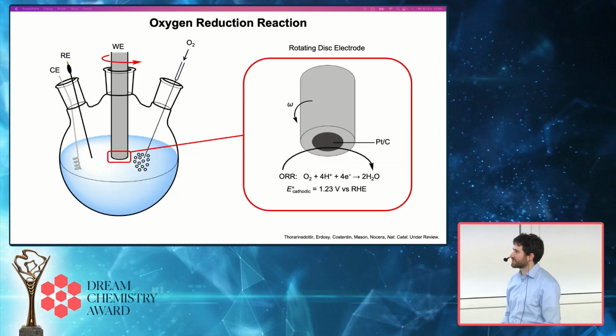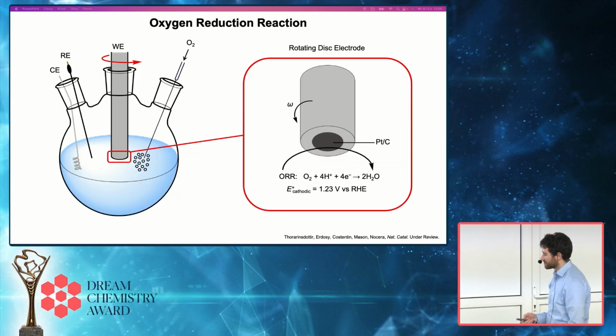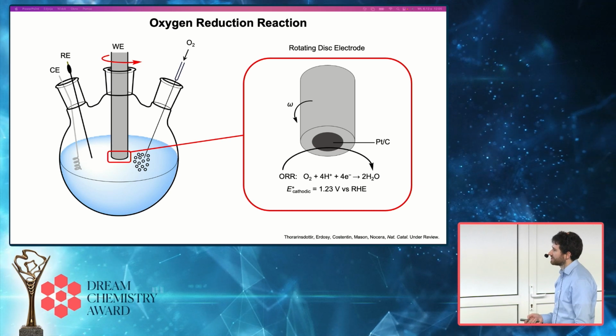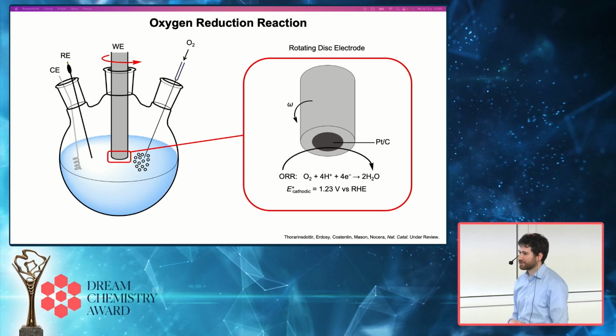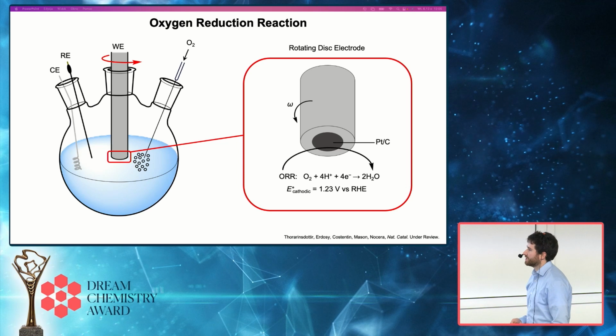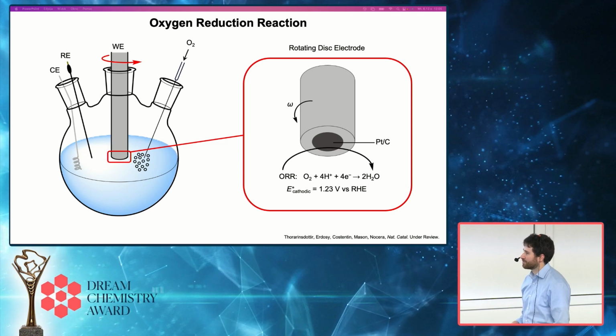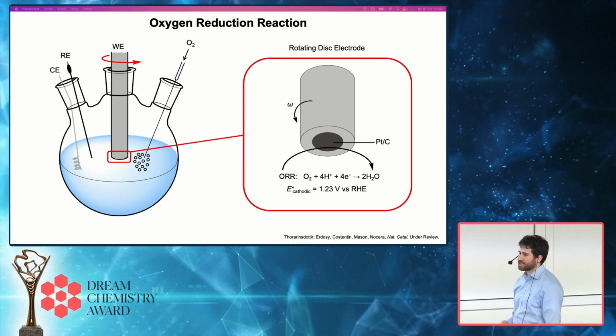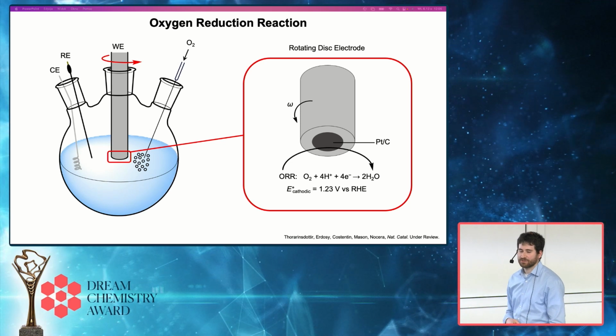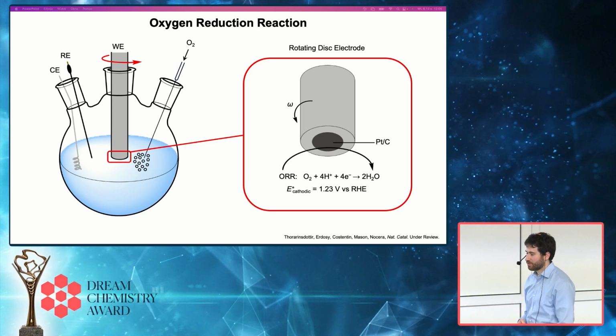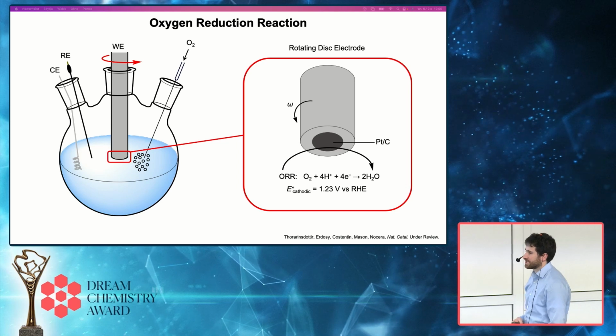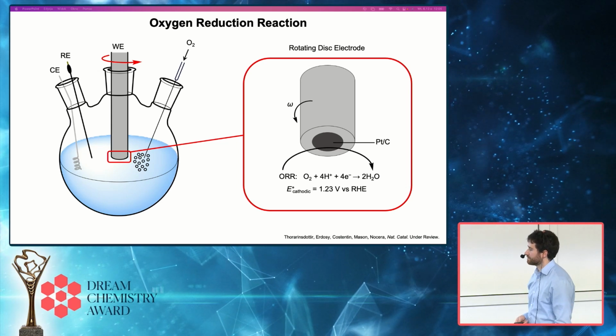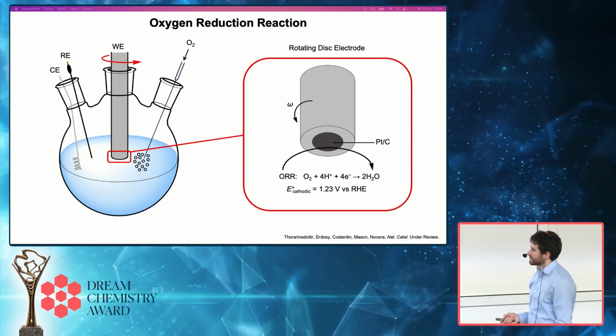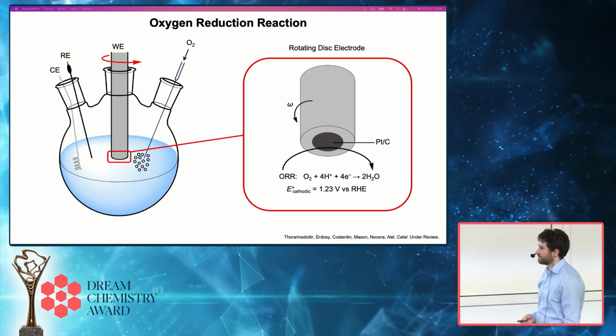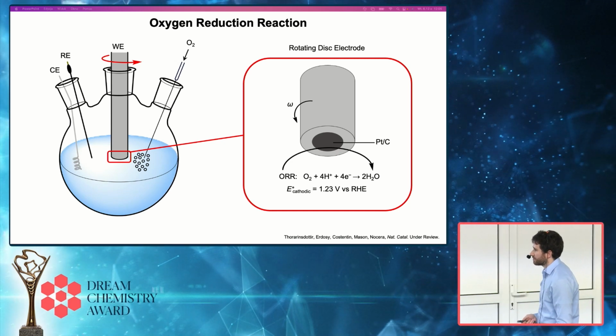And so we tested this with a simple reaction, the oxygen reduction reaction, where we're converting oxygen into water. This reaction is done commonly in fuel cells. And in conventional electrochemical setups, the reaction is very mass transport limited by the low solubility of oxygen in water. And so that dictates the current density that you can achieve under normal conditions.